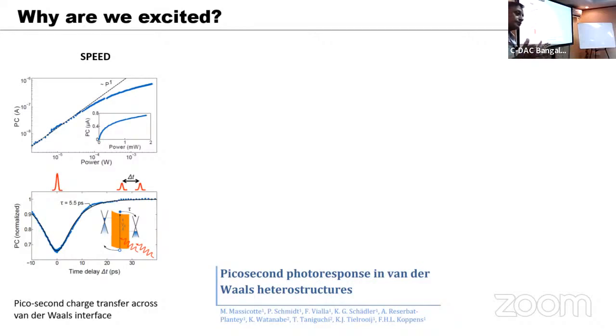of the standard single photon detector, because the electron has to travel just half a nanometer in order to be activated by light. So that's one of the huge advantages, and this has been observed. Picosecond charge transfer processes are now established in such systems.